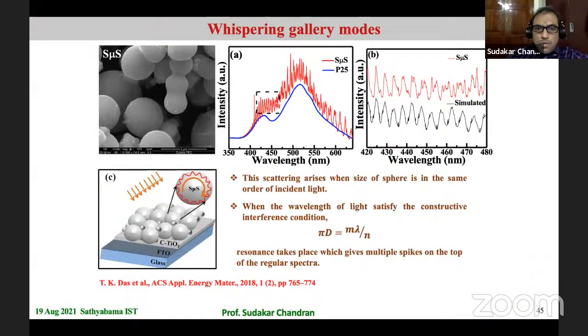So in that process, we came across this particular structure, TiO2 micron size spheres. You can see that the scale is 5 micron here. So they are typically anywhere from 1 to 5 micrometer size, and these kinds of micron size spheres do exhibit very sharp peaks when you take the PL, and these are nothing but the whispering gallery modes.